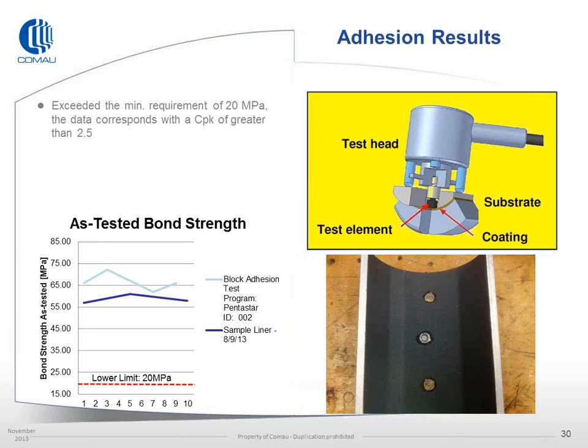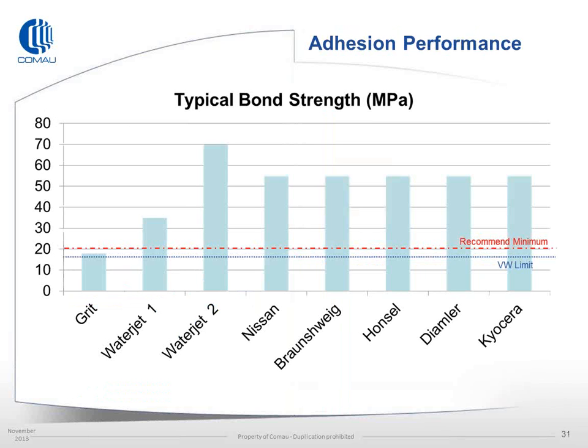And from my opinion, Volkswagen's been in production for many years with coatings below 20 megapascals. So from our side, to make calculations in terms of capability, 20 megapascal is a sufficient lower limit. If you start to pull it up, it just makes Cpk calculations harder. Most processes stay well above that limit. Now, these are just reference numbers, but everything that has been evaluated has produced adhesion results around 50.